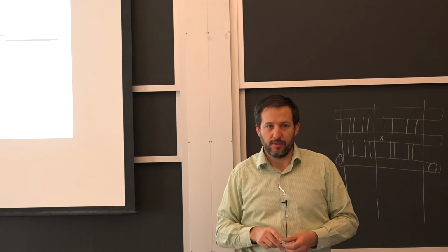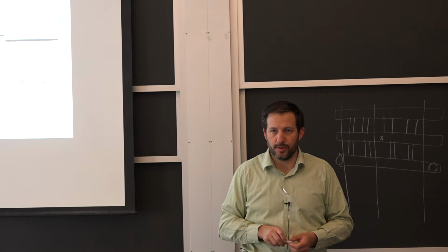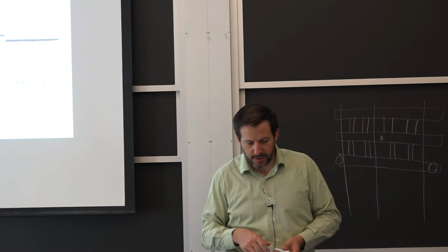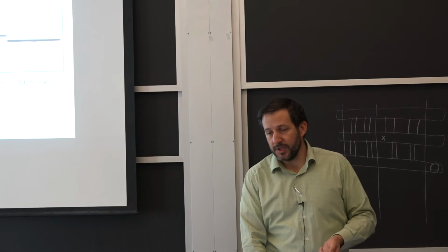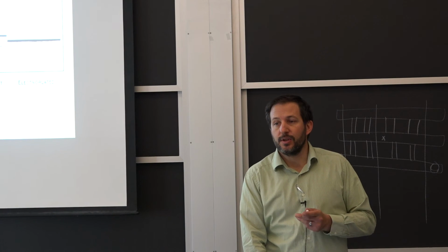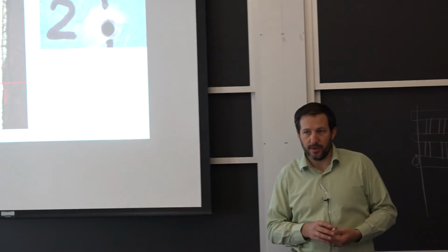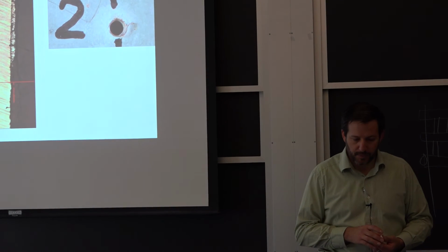It's outdoor and a little bit of a salt spray, essentially, from service. So now all of a sudden what used to be okay for sheet galvanizing doesn't last long enough, and they have to do an early replacement, and nobody's happy. So it is just this one idea: it's good to understand the process of sacrificial protection, but to determine how much you need for your application, you can't assume that if it's good enough for somebody else, it's going to be good enough for you.